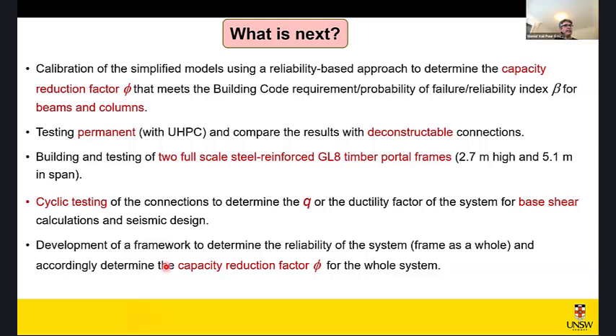Look, the way we look at it since the start of this project is I don't think the process of fabrication would be significantly different than what we see in the fabrication of glulam. There are additional interim steps that should be taken, but I believe they would not really affect the way we build this, and they would not be that different from the glued laminated fabrication process. It's just a matter of inserting steel bars and applying or extruding the adhesive layers, and then applying sufficient pressure and curing time, and that should work quite well.